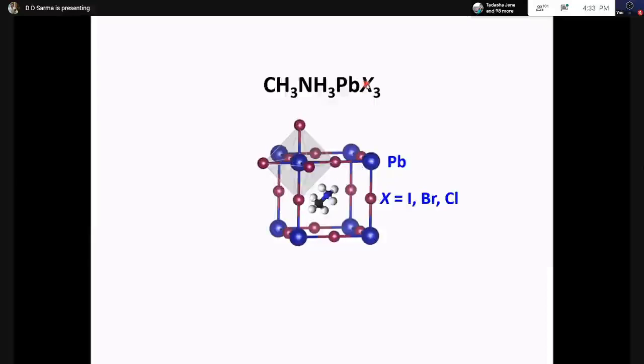This X is a halide, mostly iodine, but it can also be bromine and chlorine. It is arranged in a perovskite structure. The perovskite structure is very easy to think of. Think of a cube. At the cube corner, you put this lead, which is called the B-site metal. You put the B-site metal at the cube corners, and at the edge center, you put this halide X, which could be iodine, bromine, or chlorine.